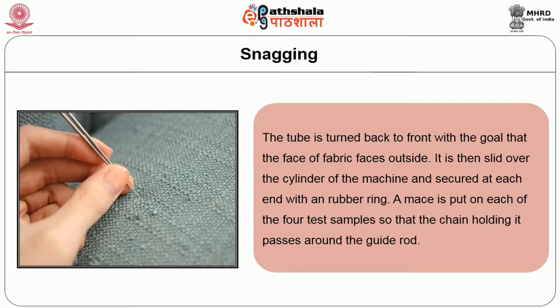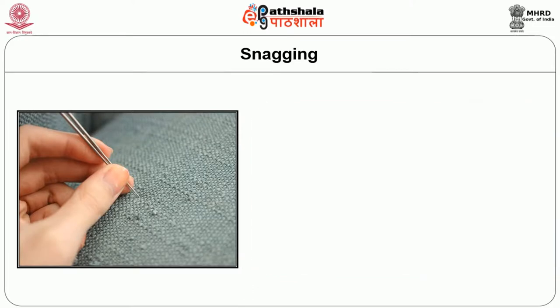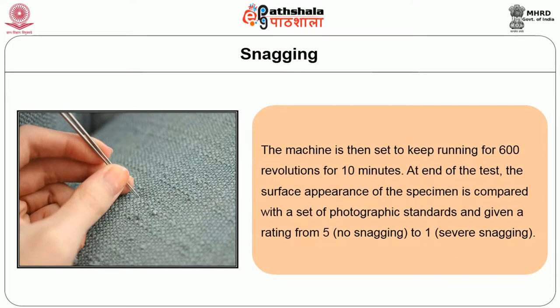It is then slid over the cylinder of the machine and secured at each end with a rubber ring. A mace is put on each of the four test samples so that the chain holding it passes around the guide rod. The machine is then set to keep running for 600 revolutions, totally 10 minutes. At the end of the test, the surface appearance of the specimen is compared with a set of photographic standards and given a rating of 1 to 5, where 5 represents no snagging and 1 represents severe snagging, and the rest lies in between. Next is abrasion resistance.